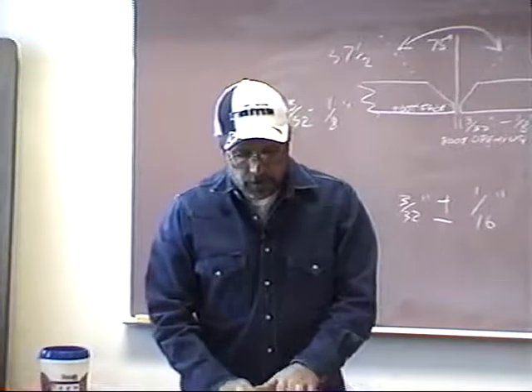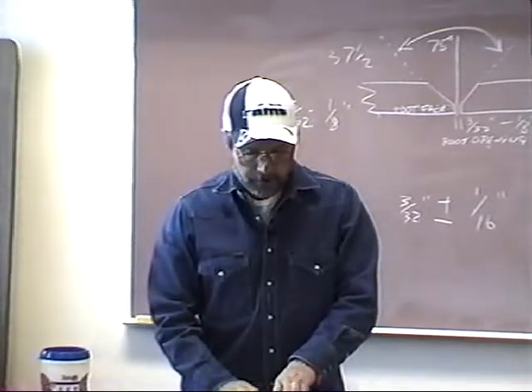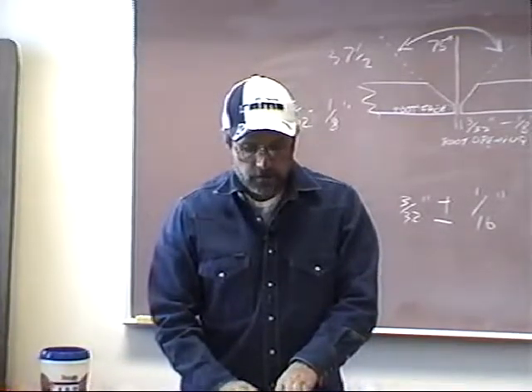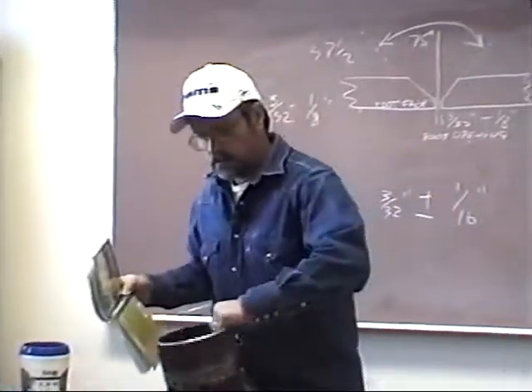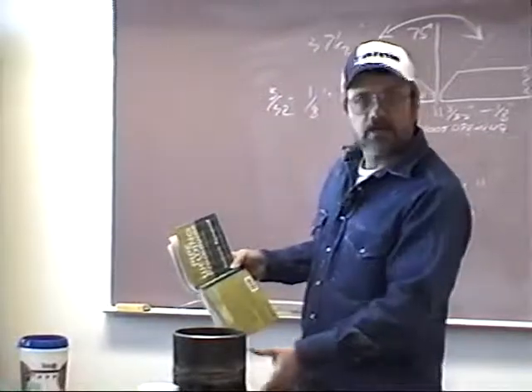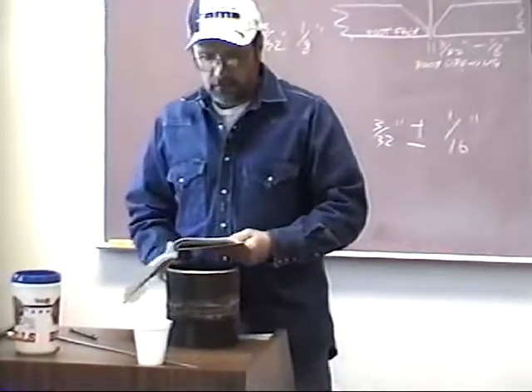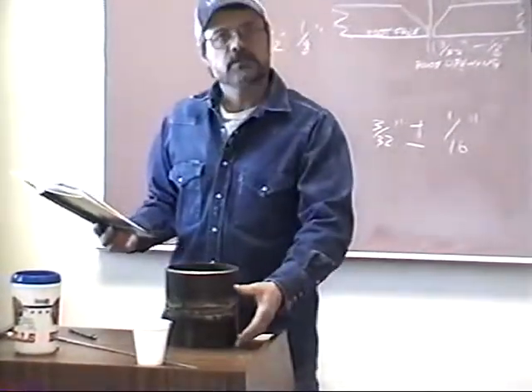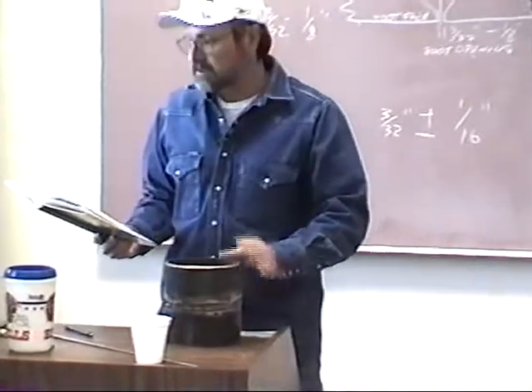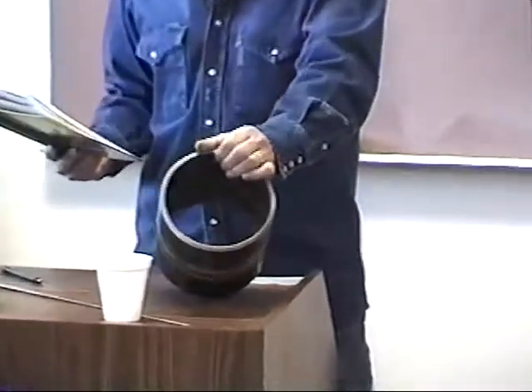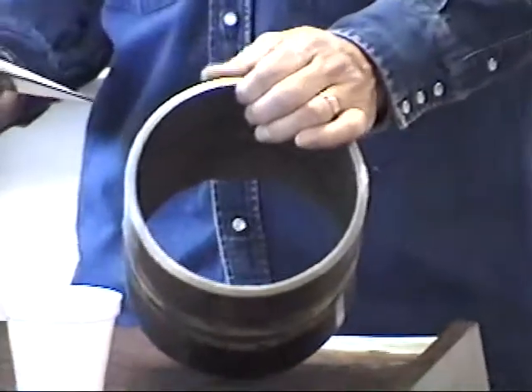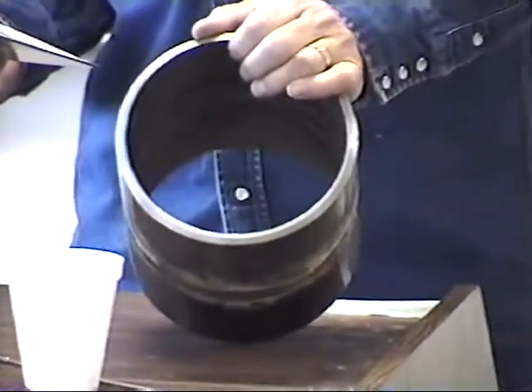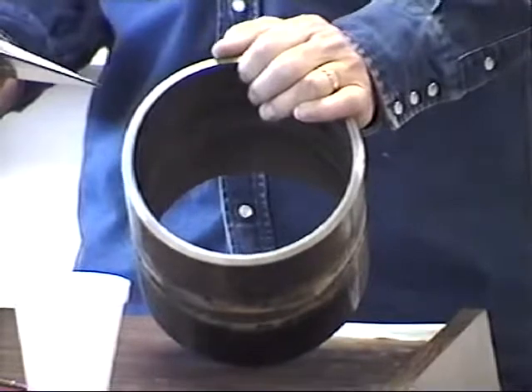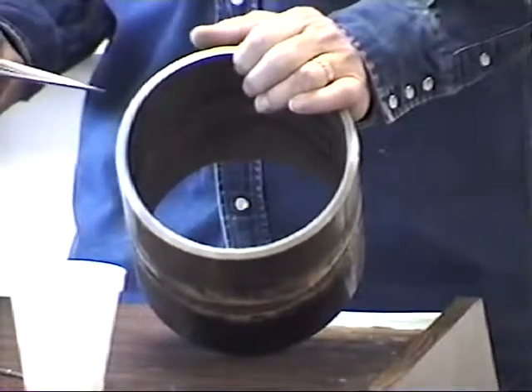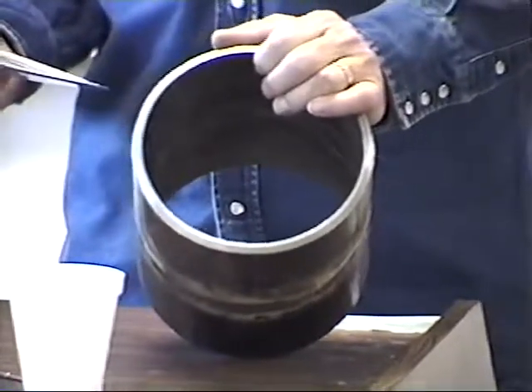In our program, in order to save material and still produce accurate, good quality welds, we use coupons that are 3 inches long, generally. Here's an example of them. They're 3 inches long, and we use 6-inch Schedule 40 and 6-inch Schedule 80. This happens to be Schedule 40, so it has a wall thickness of a little over 1/4 of an inch, 0.280. 6-inch Schedule 80 has a wall thickness of 0.432.